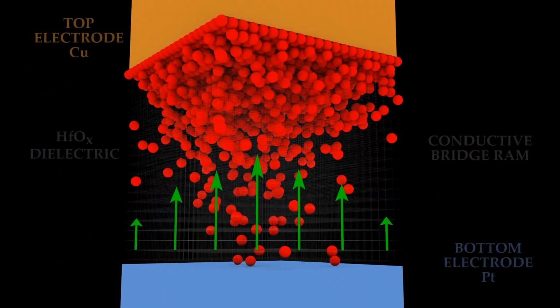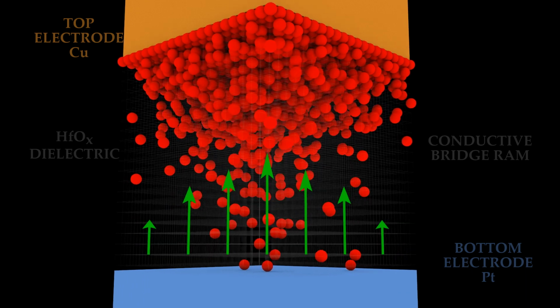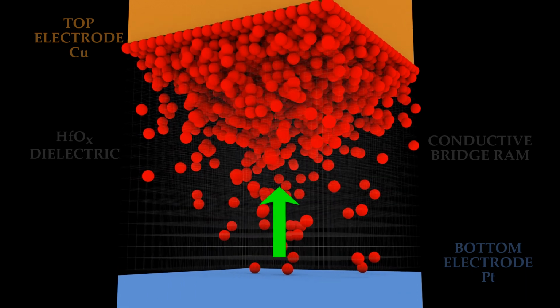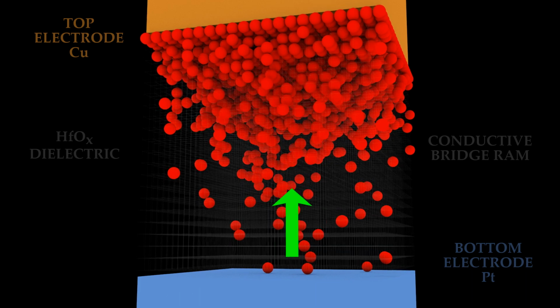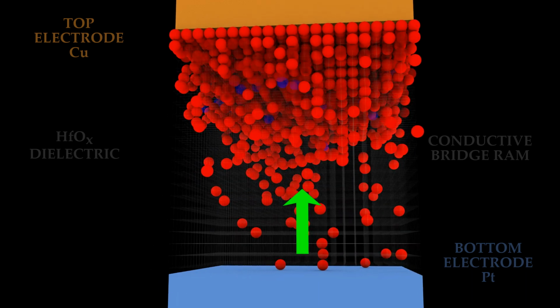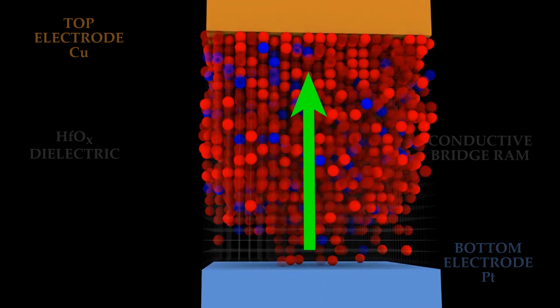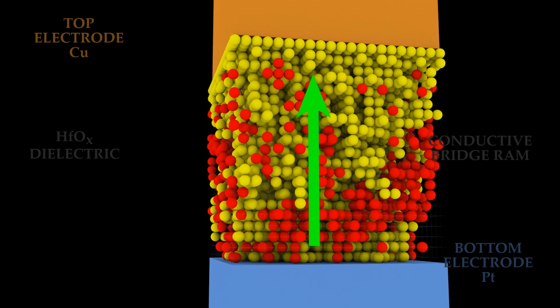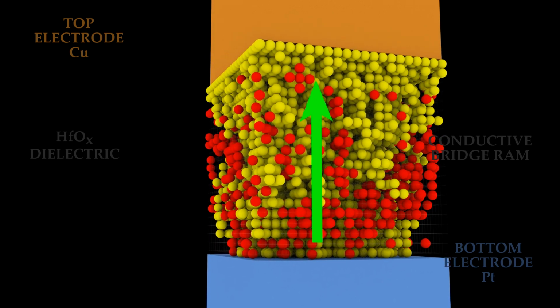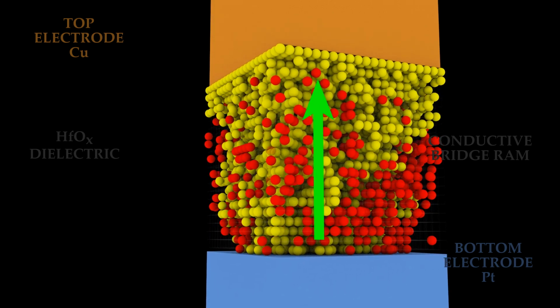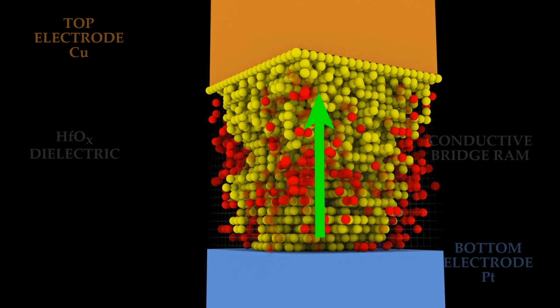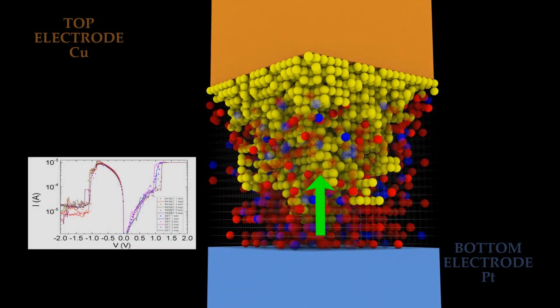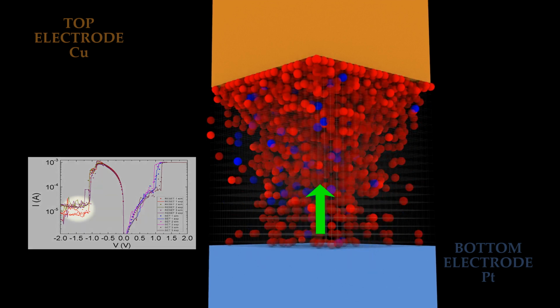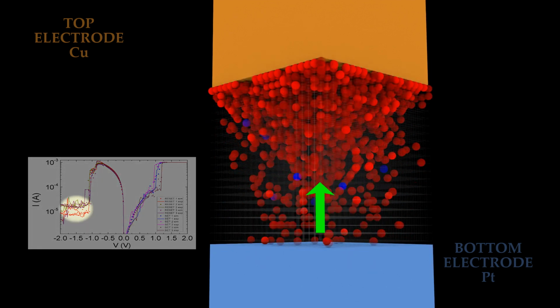The average electric field varies stochastically between the conductive filament tip and the electrode as the filament formation and destruction takes place. The dielectric conduction mechanisms depend exponentially on this local electric field, such as Poole-Frenkel and Fowler-Nordheim. Therefore, current variations can be produced at these formation stages.